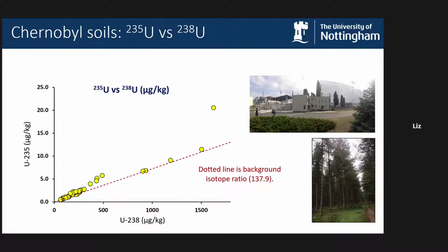But some of the soils are deviating away from that line, showing enrichment in uranium-235 and confirming that those gamma-emitting particles observed in the soils were likely to be fragments of fuel rod particles that were released in the explosion on the 26th of April 1986. Were that data just random scatter, we'd expect to see points below the line as well as above them. And from that data, we can actually accurately quantify the concentration of uranium from fuel rods in those soils.